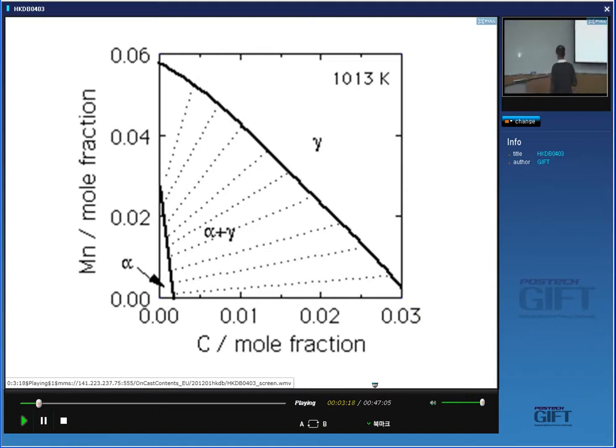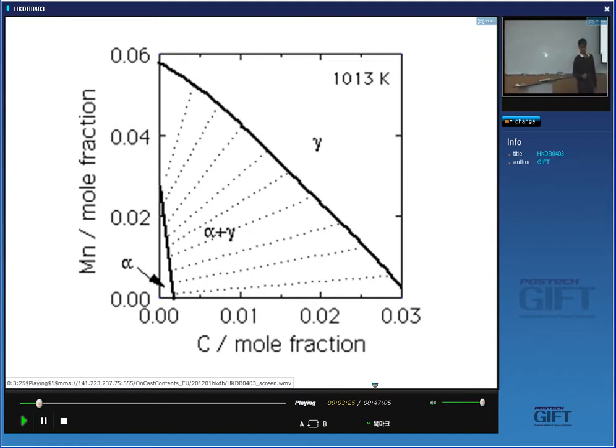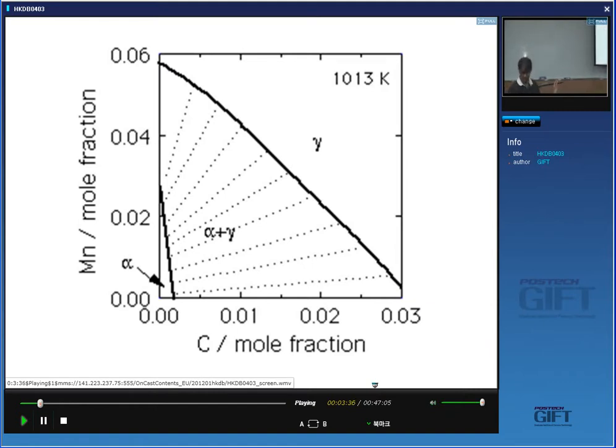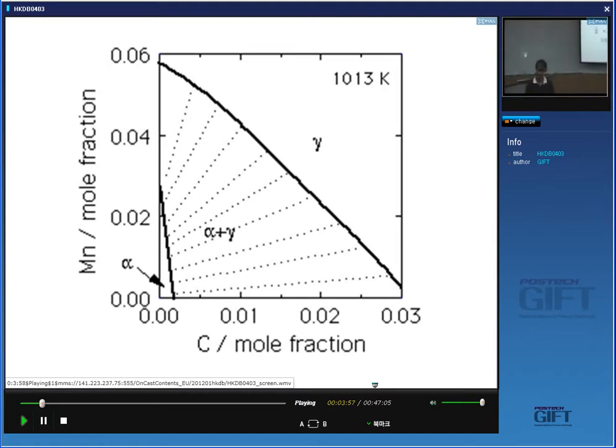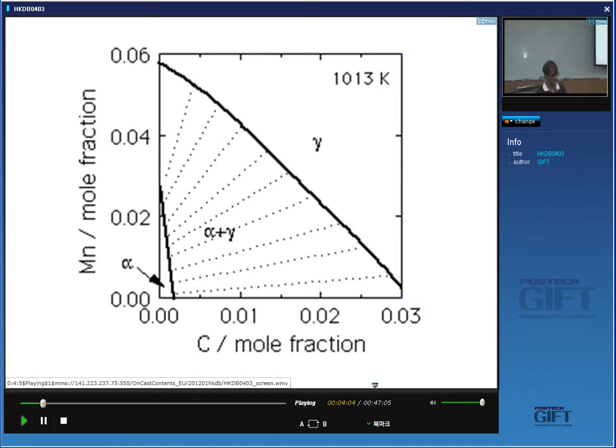This is an isothermal section of the iron-manganese-carbon phase diagram. I'm plotting manganese here on the vertical axis, carbon on the horizontal axis, and it's at a constant temperature. And yet we have all these tie lines which define ferrite which is in equilibrium with austenite. For the purposes of this lecture, I'm assuming that we can calculate this phase diagram, and we can use a variety of software that's available to do that. The calculation of phase diagrams is completely based on experiments — you do thermodynamic measurements, create thermodynamic databases, and that allows you to calculate the tie line compositions.